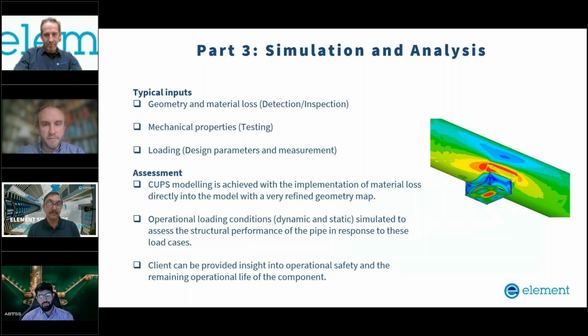We can very accurately have those corrosion maps and the pitting maps and the local inspection of those areas of pitted regions identified by Basab with the local crack-like features, and we can take all of that into account. We can take those corrosion maps, areas of generalized corrosion, areas of localized corrosion with the pitting, and also take into account the very specific morphology of the crack-like features, and feed that all into our simulation, which is what we did here.